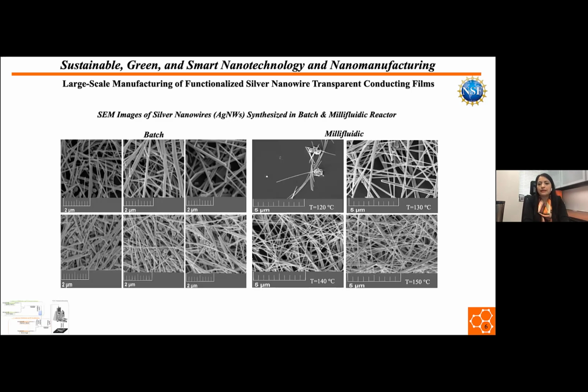As you can see here, there are a couple of SEM images of the silver nanowires that we are producing in our lab. The 6 SEM images on the left-hand side of this slide show the silver nanowires produced in a batch reactor. Even though the reaction conditions were exactly the same for all of these 6 reactions, we were not able to get 100% nanowires without any other nanostructures, which means that we cannot have precise control over the size, morphology, and size distribution of silver nanostructures produced in a batch system.